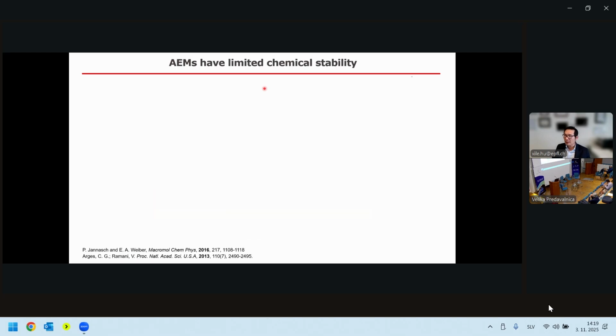The second problem is chemical stability, okay? Now, chemical stability is typically thought in terms of hydroxide because we are dealing with alkaline condition. Now, there are many reactions hydroxide can do because hydroxide, as chemists will understand, is a really good nucleophile, okay? And so if you take hydroxide, you do nucleophilic substitution. If your structure has a benzylic bond, and this is important because many of these polymers, for attaching this anionic group, you need a benzylic moiety. And for benzylic one, of course, you can actually do a substitution. You make a benzylic alcohol, so that's not really good.